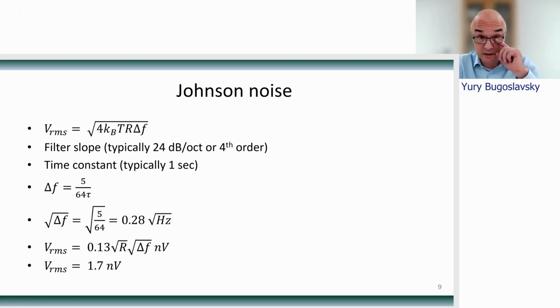The bandwidth is determined by the measurement electronics, and in the lock-in, we're using two filters. The input bandpass filter is typically set to the 4th order or 24 decibel per octave. The output filter is usually conveniently set to 1 second time constant, which is good for our typical measurement frequency of 20 Hertz. It's a matter of mathematical derivation to show that with this combination of filters, the effective bandwidth is equal to 5/64 Hertz. Now, substituting the coil resistance, which is 2 kilo ohms, and room temperature into the formula, we arrive at the result. The fluctuating thermal voltage across the coil is equal to 1.7 nanovolts.